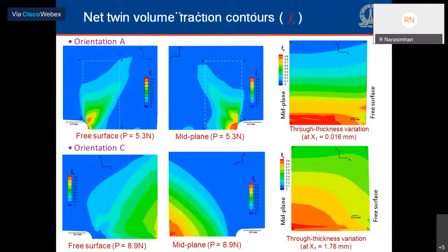These are contours of twin volume fraction corresponding to orientation A and orientation C. And what I have shown here is the contours on the free surface of the specimen at the midplane, as well as through the thickness on the right side, taken on a plane ahead of the notch tip. Those are the three images which you see in each row. The top row is for orientation A and bottom row is for orientation C.